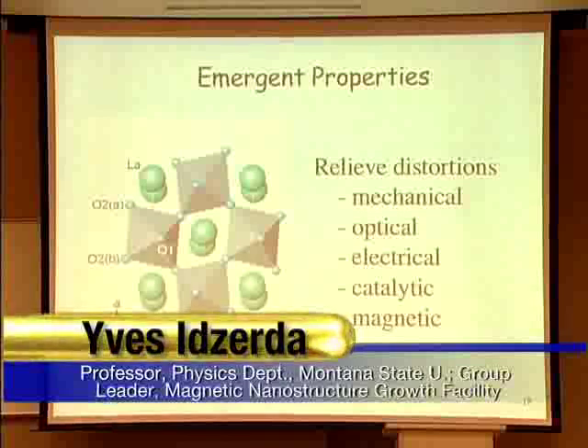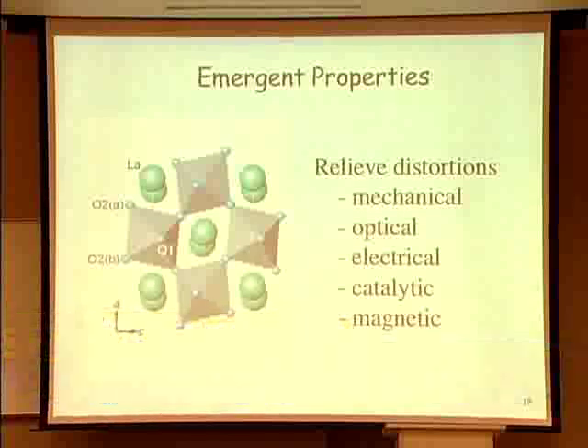That buckling leads to interesting properties on the macro scale. When I get small, that buckling goes away. Everything can relax back into the space that it wants. When that happens, the properties change dramatically. And that's what we're looking for: changes in mechanical, optical, electrical, catalytic, magnetic properties just because I've made this thing relax and go back into what is considered a more normal state, and an emergent property shows up. And in this case, the length scales are nanometers because I can't have too many atoms, otherwise they're forced into this confined geometry. So one of the things we look for is that kind of emergence.